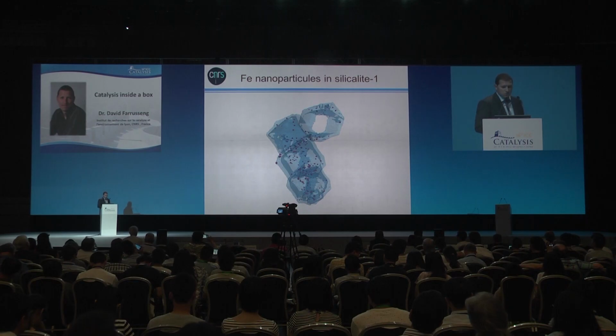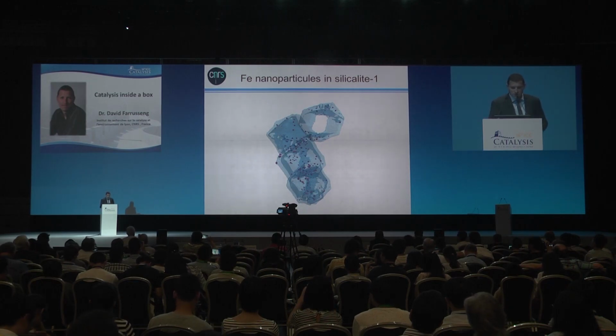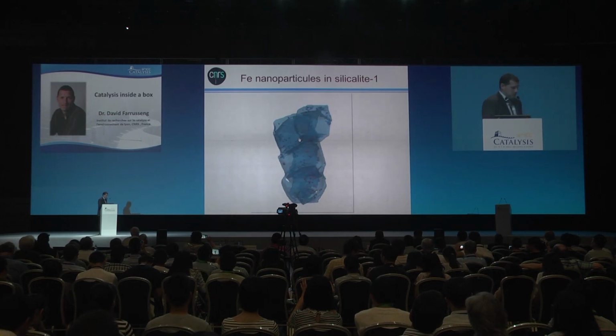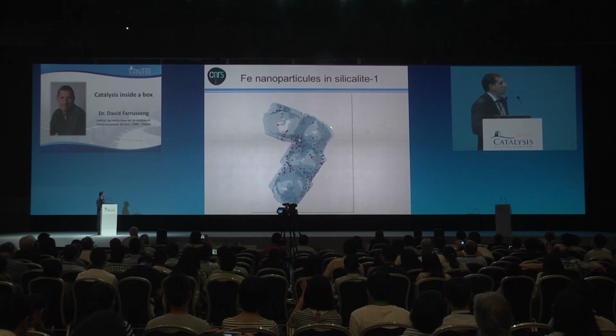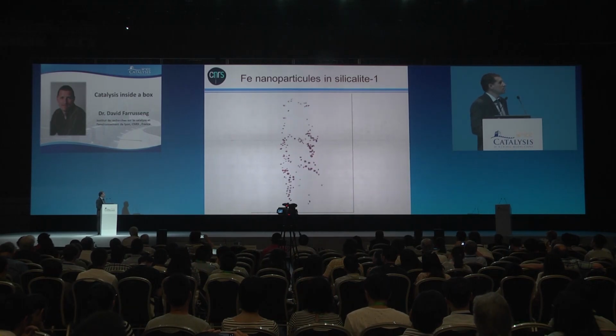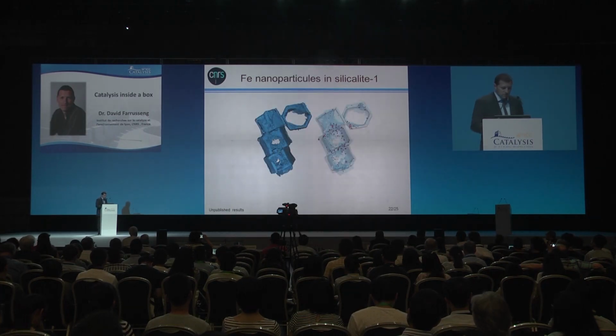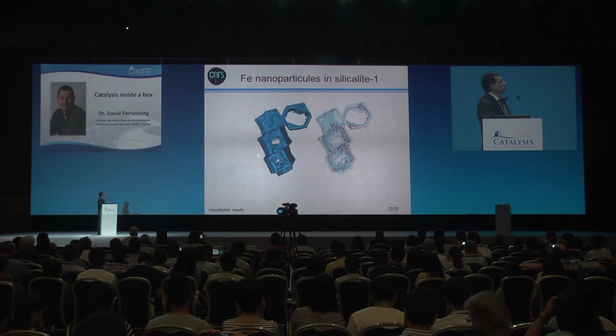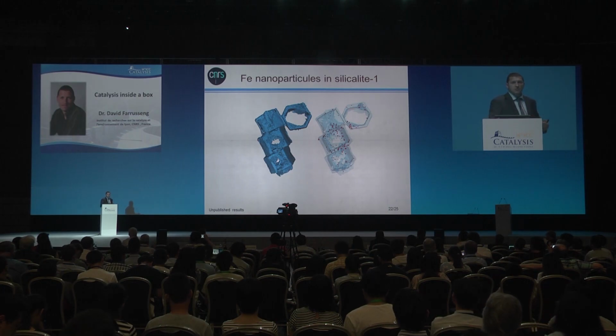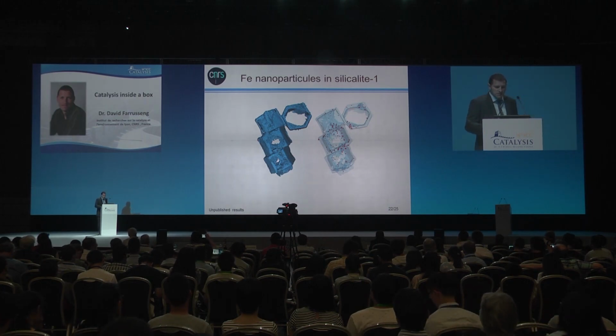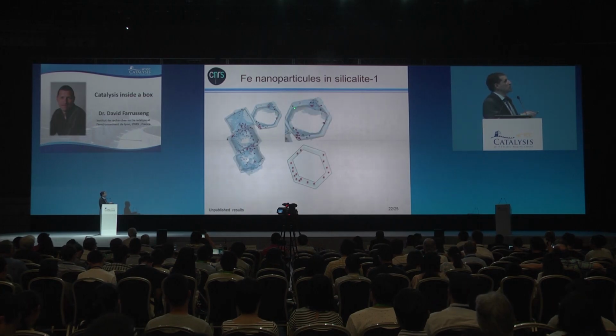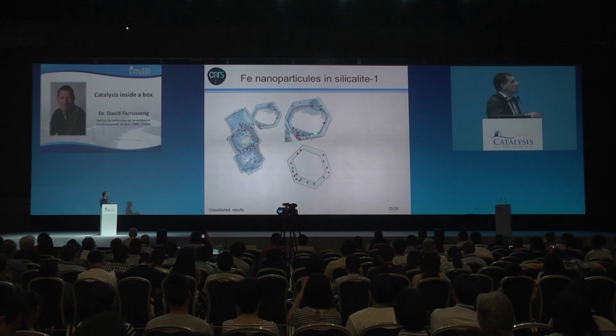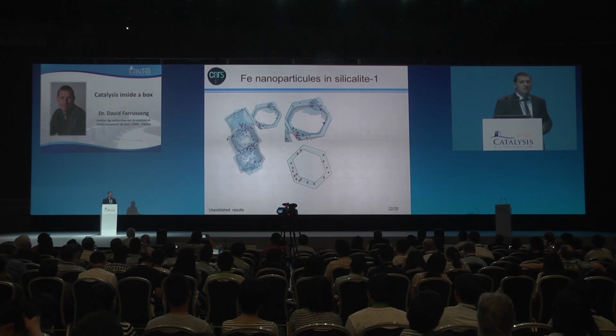So we did a tomography analysis. I will try to run the movie. Yes. The blue is obviously the zeolite cavity, and the red spots are the iron particles. If you look closely, you can find hardly any red points either on the external surface or on the inner surface, meaning that all the nanoparticles are embedded within the shell. All the nanoparticles are protected in the shell. It is very important for the catalytic properties, as you will see here.